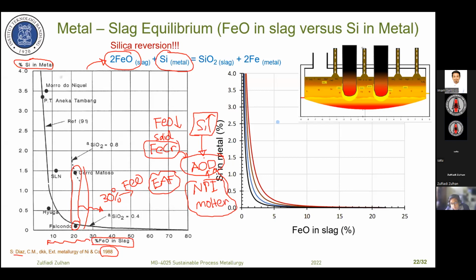We charge the NPI, blowing oxygen, and we have an advantage from the silicon content in the NPI during the oxygen blowing. Oxygen reacts first with silicon, and this reaction is exothermic, so we can produce heat. The temperature of the metal in the AOD converter will be high. In that case, the energy is enough to charge the ferrochromium. So this is the advantage of the silicon content.